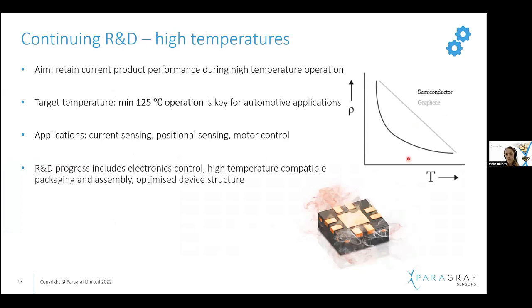And this rough sketch just illustrates the advantage of graphene with its more linear resistivity behavior over a range of temperatures. We're not seeing any sudden and sharp changes, so it's much easier to have a handle on over a range of temperatures. So the temperature that's our aim currently needs to be a minimum of 125 degrees Celsius. And this is because of automotive applications having this requirement. So again, a range of areas within that this could be used for.